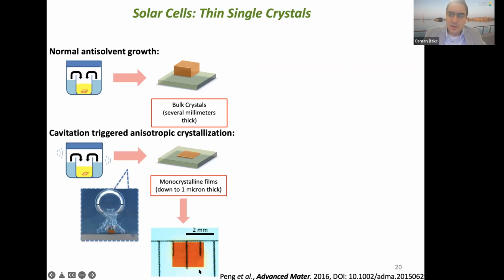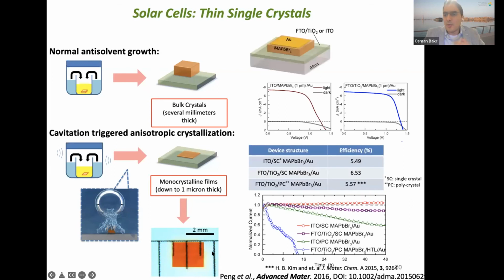millimeters in lateral dimensions. And what that allowed us to do was to study the first single crystal film solar cell. What that showed us is that perovskite single crystal cells are actually relatively stable. And what makes them unstable is actually the different layers that we add, different device layers that react with the perovskite.